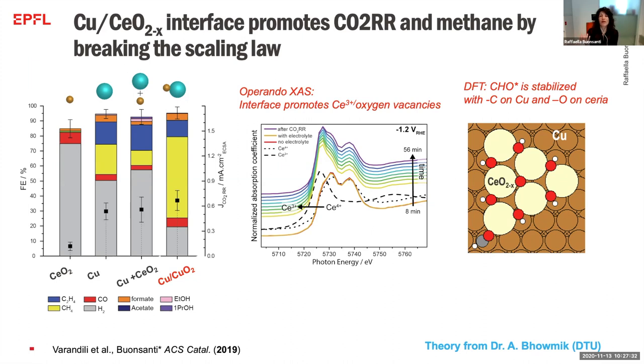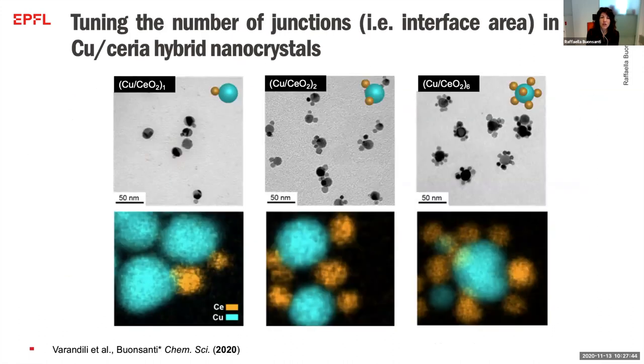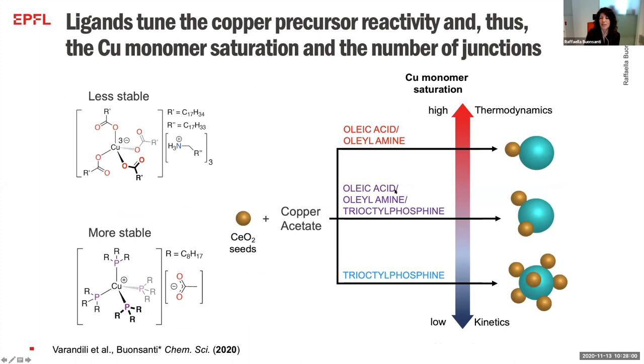And at this point, we wondered, well, maybe if we increase the interface area further, we can improve further the performance. So again, Denaz was able to play around with the chemistry and to have not only one sphere of ceria, but more spheres of ceria surrounding the copper domain. The way in which she did it is to play with the chemistry and to substitute different ligands. In this case, the ligands that she uses contribute to form different complexes with the copper, and these complexes have a different stability during the reaction, and they lead to different products.